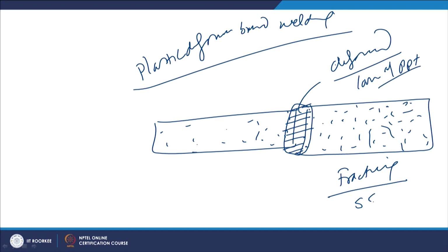So, basically we get a solid solution through the complete dissolution of the precipitates, while the heat generated during the plastic deformation based welding process can lead to partial dissolution in the heat affected zone on both sides. So, in this case the complete dissolution takes place in the weld metal due to the fracturing and complete reversion of the precipitates, while partial dissolution or partial loss of the precipitates takes place in the heat affected zone.